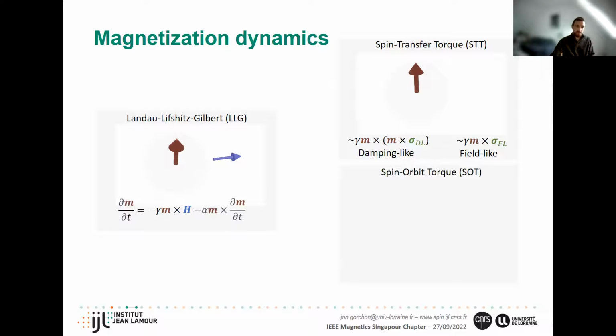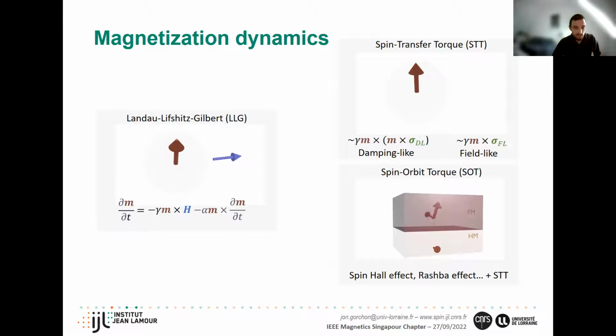Another, a third way, let's say, of inducing dynamics is the famous spin orbit torque. Here the idea is that we're also going to use the STT, but to generate the spin current, we use either a heavy metal or an interface with large spin orbit coupling. So when you send a charge current, you get a spin current that is generated transversely. And when the spin current is injected into the ferromagnet, it induces a spin transfer torque. The way to convert the charge current into a spin current, there's a number of effects. You can have the spin Hall effect, which is a bulk effect, or the Rashba effect. So we're going to be exploiting these different effects to try to induce dynamics, but at ultrafast timescales.